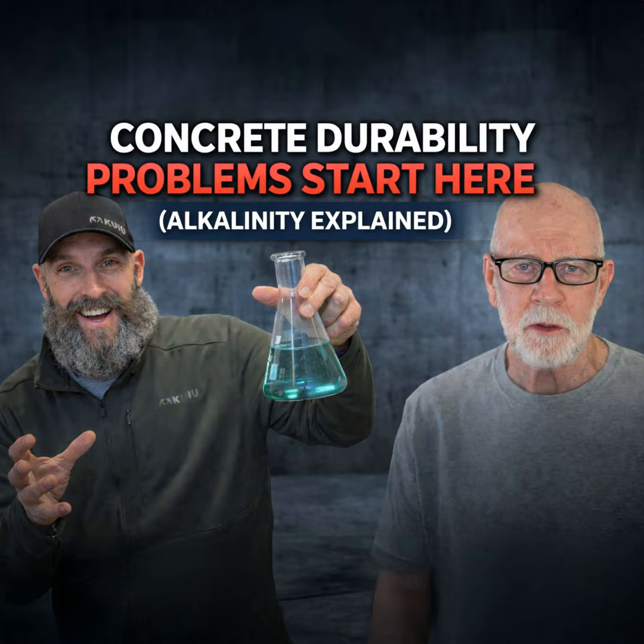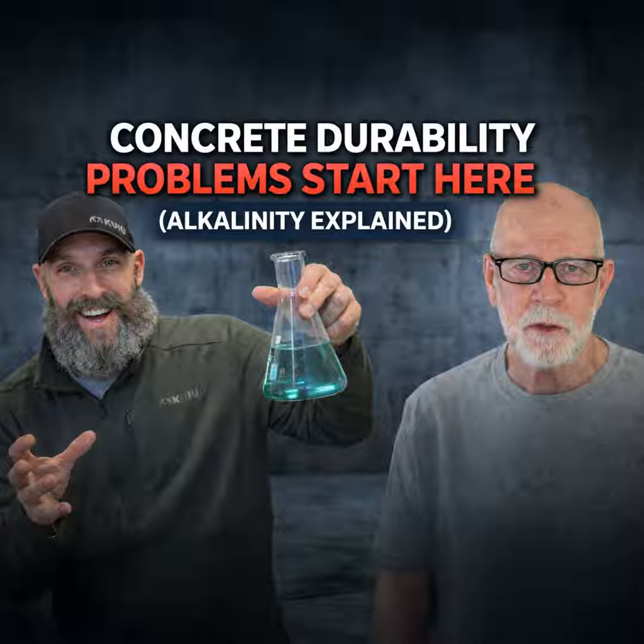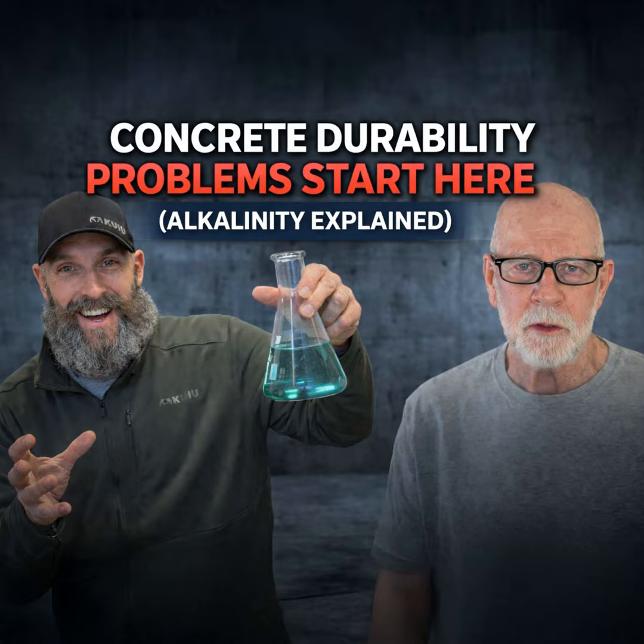They put a bag of calcium chloride in a closet and it's trying to dry everything out. And that's why it keeps things from getting mildewed. There's no difference. That's exactly what it's doing. That's a passive effect. So when people hear, well, it's vapor emission, they think it's water vapor freely coming out of the concrete. That's not true. All it's doing is trying to balance the environment within that lid. It's pulling the moisture from the air, and it's collecting on the surface of the concrete because of the salt that's inside the concrete. Exactly.